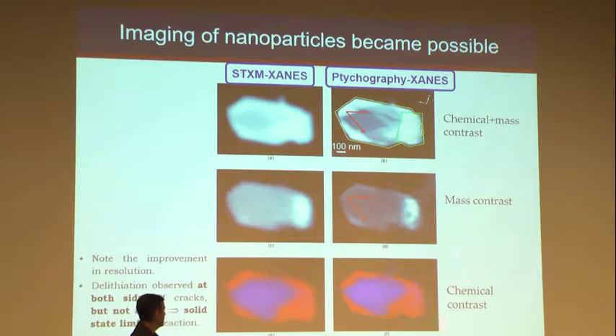You will notice first that these particles are already smaller. They're no longer 4 microns, they're sub-micron in the longest dimension. And we're comparing the standard STXM with XANES and the ptychography with XANES. So the same crystal measured both ways and what it looks like. And so the way I like to describe this is that if you take the images on your right and you squint your eyes to make your vision blurry, it looks like the image on the left. So that's what spatial resolution does for you.